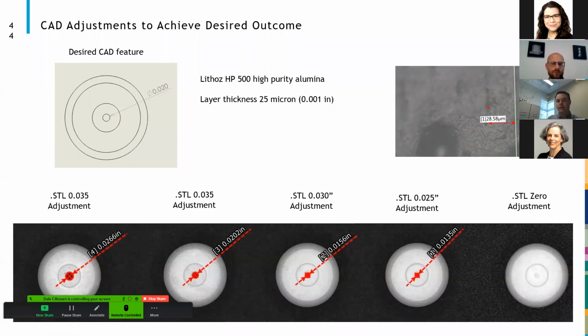As seen, the initial component had overpolymerization within the internal hole, with zero adjustments to the STL or CAD file. To accommodate this can be done by doing two different things. One, you can change the settings within the machine to adjust the pixels to where it accounts for the overpolymerization. The overpolymerization, if adjusted on the pixel settings, can affect the outside diameter. The outside diameter was within tolerance for the desired component. So to not adjust the outside diameter, we adjusted the CAD to meet our requirements, creating our own internal guidelines on printing very fine, delicate through holes through this component.